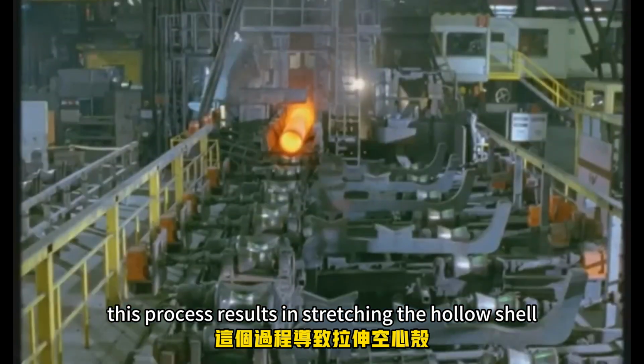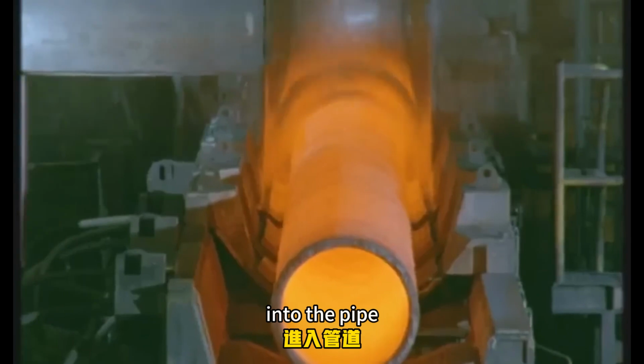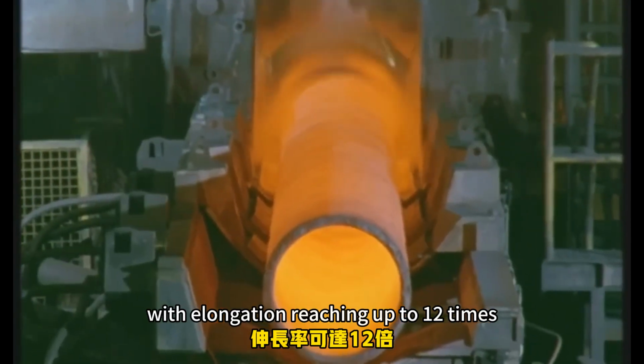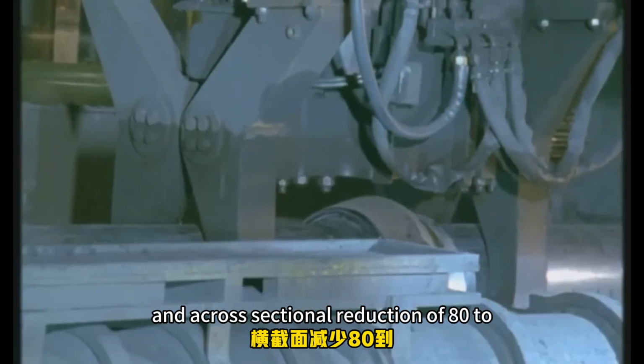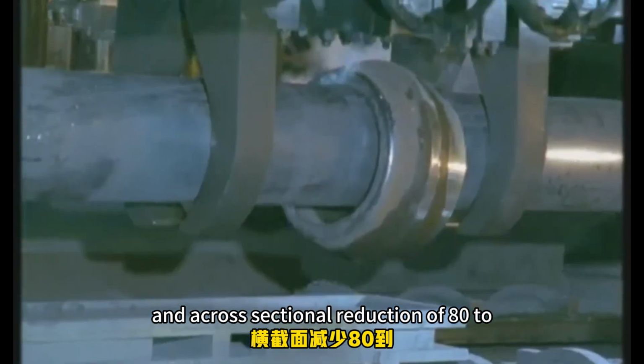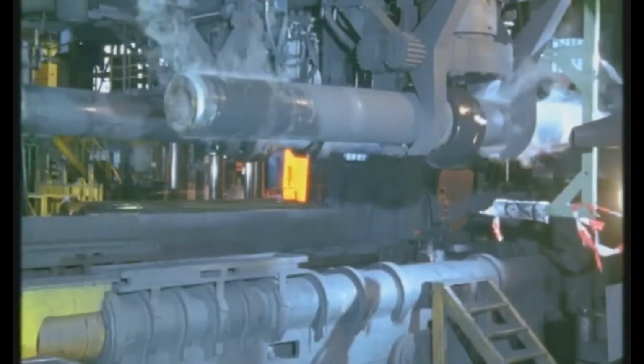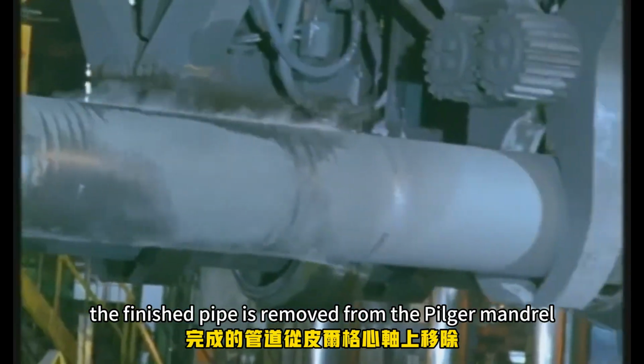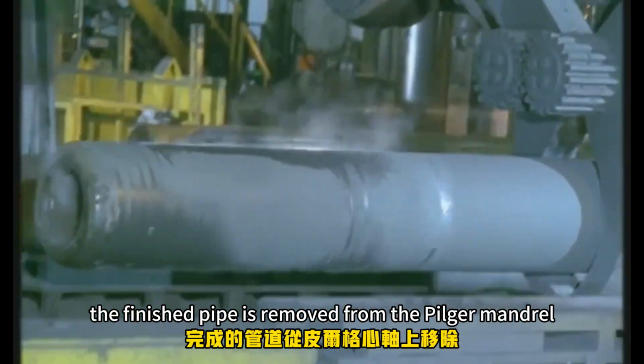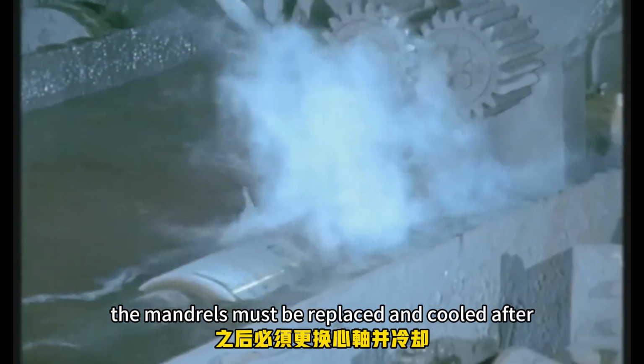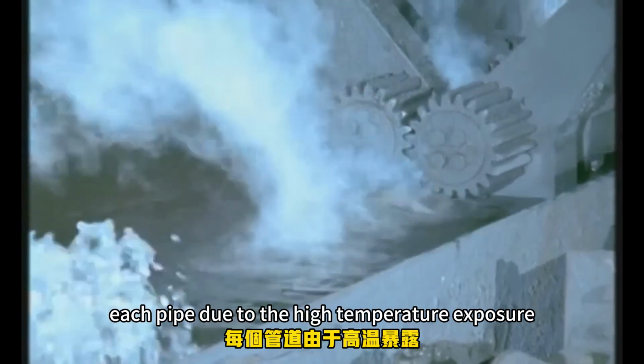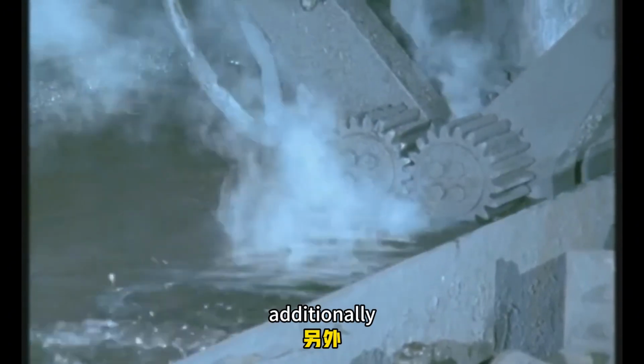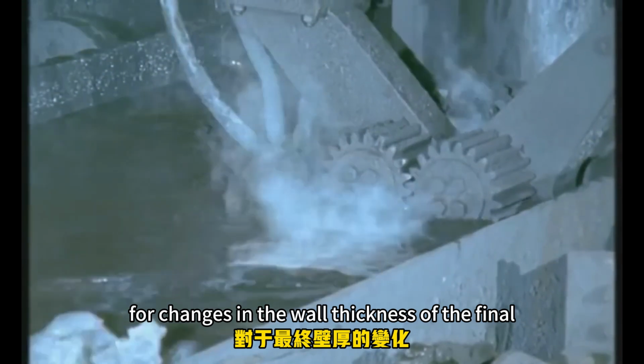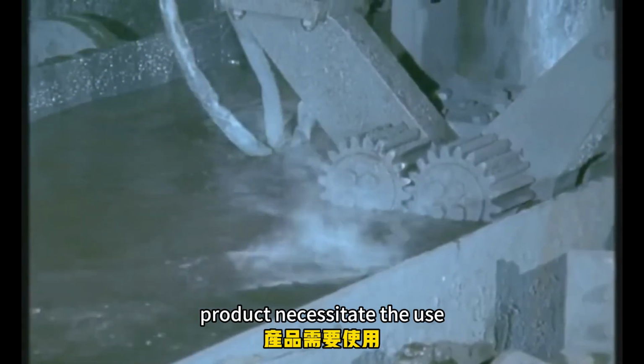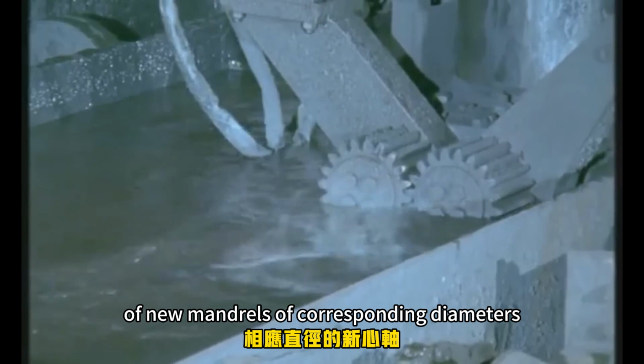This process results in stretching the hollow shell into the pipe, with elongation reaching up to 12 times the hollow shell length and a cross-sectional reduction of 80 to 90%. After rolling, the finished pipe is removed from the pilger mandrel. The mandrels must be replaced and cooled after each pipe due to the high temperature exposure. Additionally, changes in the wall thickness of the final product necessitate the use of new mandrels of corresponding diameters.